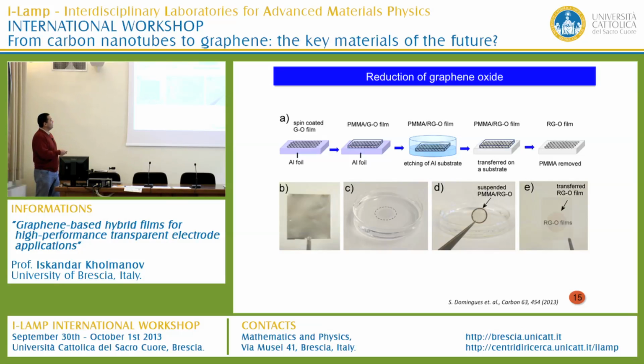We also recently developed a method in which we simply deposited graphene oxide from solution on top of aluminum foil, and we put this in a hydrochloric acid solution. Hydrochloric acid etches the aluminum foil. At the same time, it produces hydrogen that can react with the graphene oxide and efficiently reduce it. So we can obtain the reduced graphene oxide suspended, supported by a PMMA layer, and you can transfer this reduced graphene oxide onto any type of target substrate.